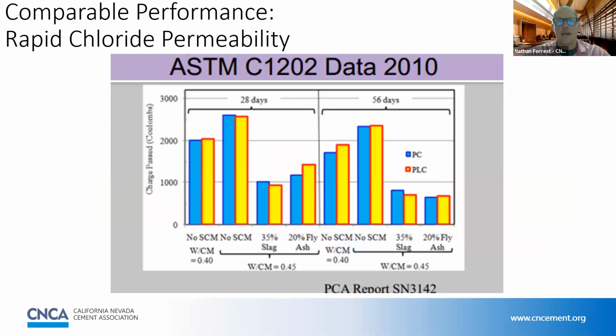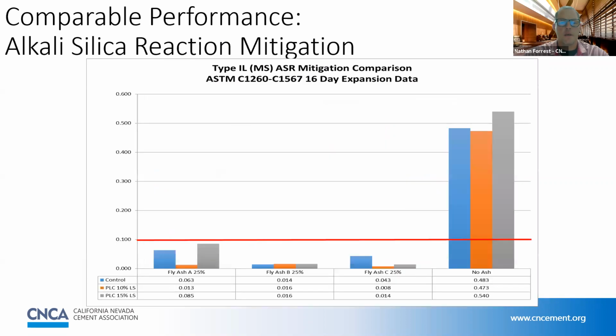Next up, we'll look at some durability aspects, including chloride permeability, ASTM C1202. The 2 graphs that we have here depict permeability at 28 days and 56 days. And like the graph before them, we're looking at Portland limestone cement in yellow and Portland cement in blue. And we have 3 different cementitious packages again. We have no SCMs at both 0.40 and 0.45 water cement ratios. Also have 35% slag and 20% fly ash. And the story continues. The performance of the Portland limestone cement in all cases is comparable to that of ordinary Portland cement.